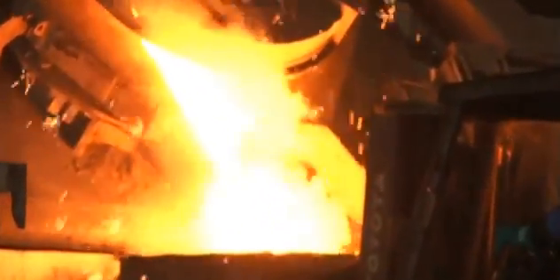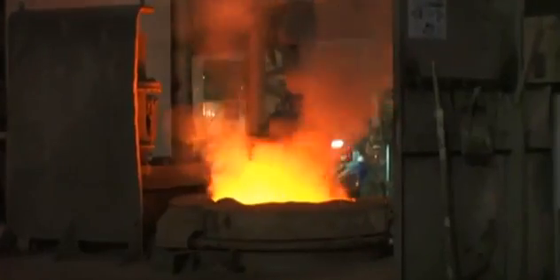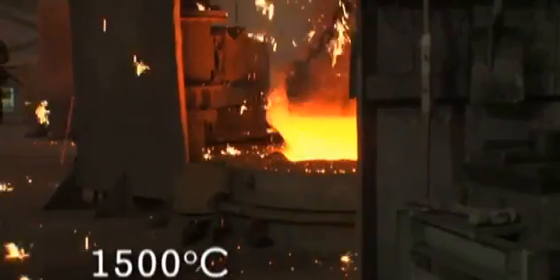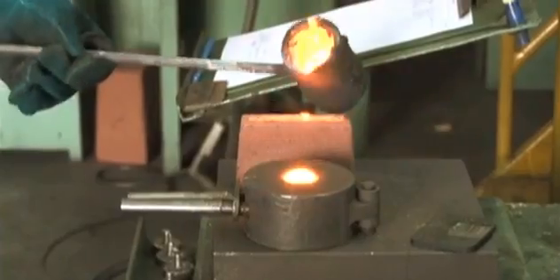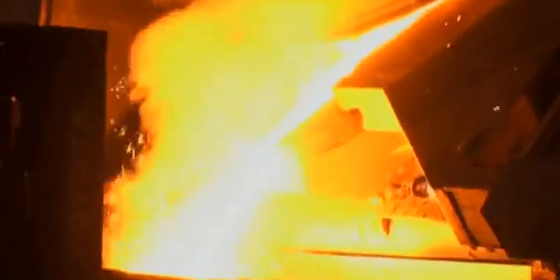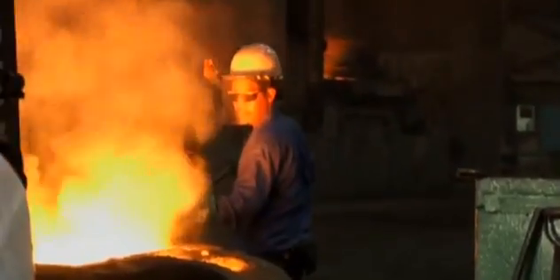Where things start to heat up — furnaces melt scrap metal charged with other additives to precisely 1,500 degrees Celsius. To maintain the quality of molten metal used, frequent samples are taken and tested using a spectrometer chemical analysis at the lab. Once given the OK, molten metal is poured into a one-ton ladle and transferred. Impurities in the metal, commonly known as slag, are constantly removed, and the metal is kept at 1,420 degrees Celsius — the minimum temperature to pour into the mold.